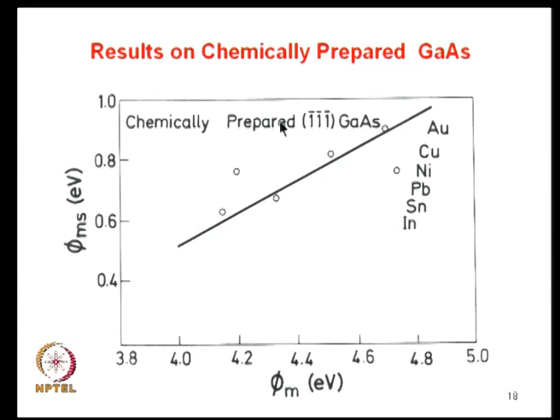Okay. Now, another surface, 111 or that family, where they chemically prepared it. Chemical treatment you give. Then, when phi m changes from 4 to 4.8, instead of a 0.8 electron volt increase in phi b n, it increases something like about 0.3 electron volts. So, still almost a linear variation is there with phi m, but not as much as you expect. Everything points out that if the interface state densities are high, the phi b n will become independent of phi m. But if the interface state densities are reduced to some extent by some passivation, it will become proportional to phi m, but not as much as, there is a proportionality constant, a factor which is not equal to 1, but less than 1.